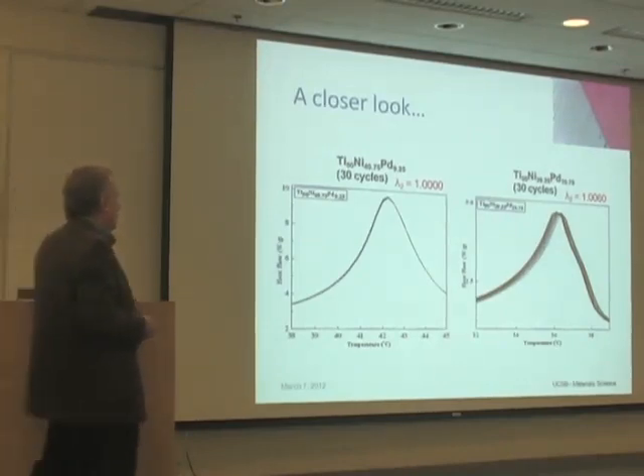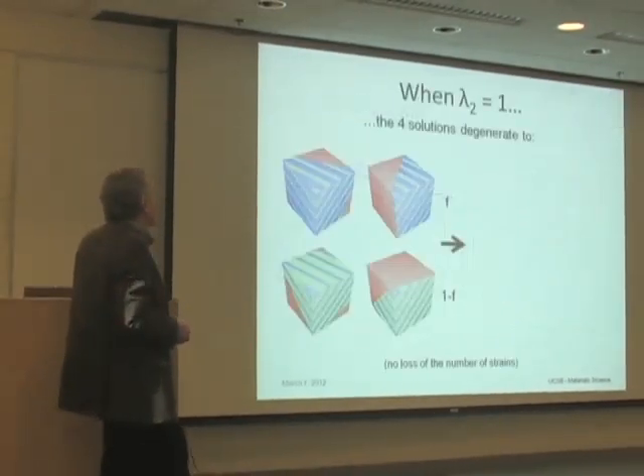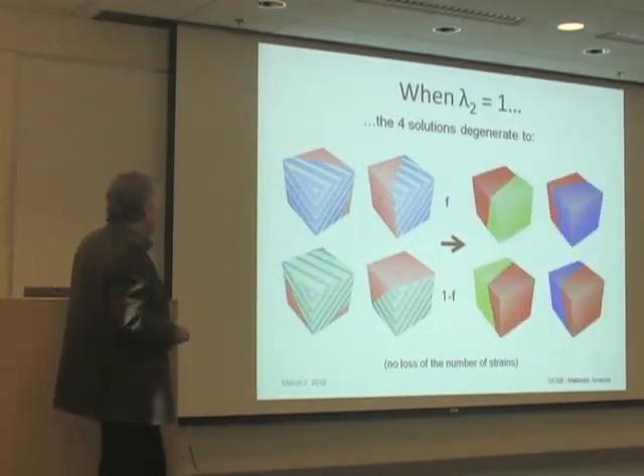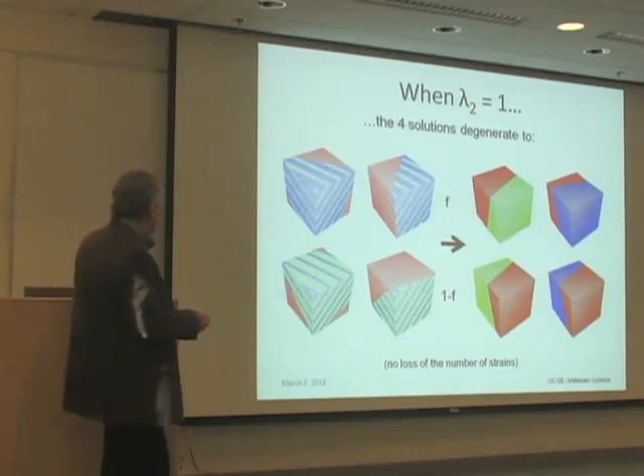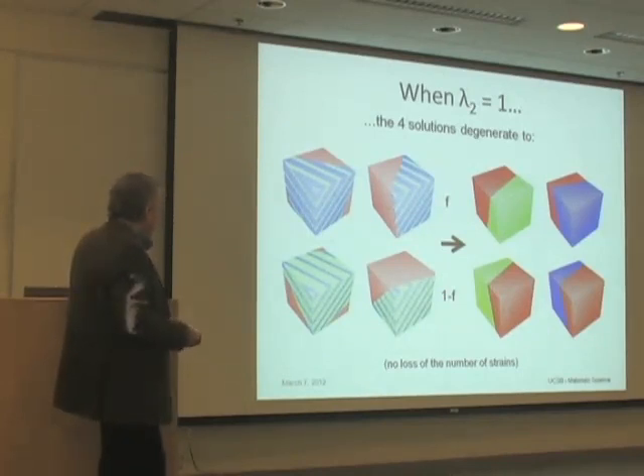Okay, so again, there's the picture. So this is what happens when lambda 2 is 1. The four solutions of the crystallographic theory that I described earlier, 4 per twin system, they reduce to these 4. So in addition to losing the transition layer, and you get these single variant interfaces, there's no loss in the number of strains. You know, there's sort of 4 average strains over here. There's 4 strains over here.